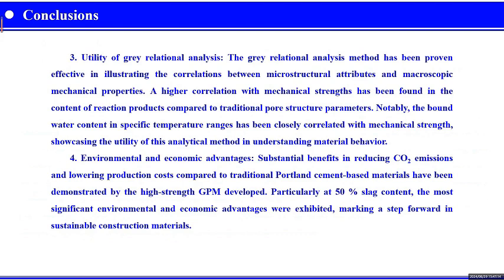The third, the gray relational analysis method has been proven effective in illustrating the correlations between microstructure attributes and macroscopic mechanical properties. A higher correlation with mechanical strength has been found in the content of reaction products compared to traditional pore structure parameters. Notably, the bound water content in specific temperature ranges has been closely correlated with mechanical strength, showcasing the utility of the analytical method in understanding material behavior.